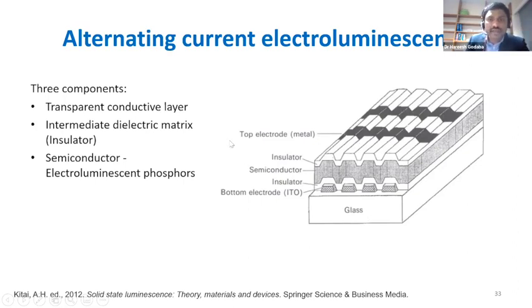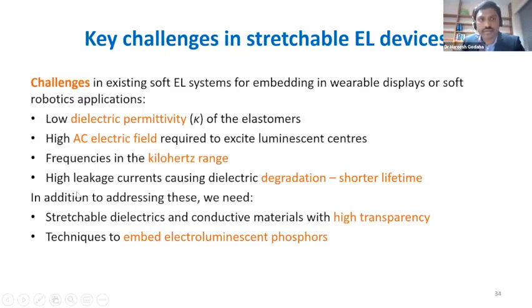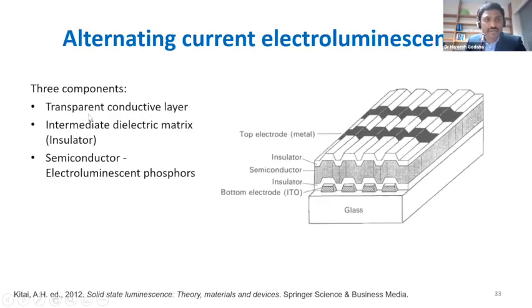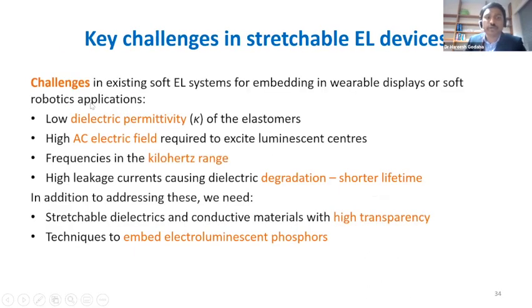Okay, and now if you want to make an ACEL device that is actually stretchable, the challenge is that all these parts need to be stretchable, right? So the key challenge in developing a stretchable electroluminescent device is that we need this dielectric matrix, right? For most soft materials, the dielectric permittivity of the elastomer is low, which may result in low luminescence. And because of that, we need a high AC electric field to excite the luminescent centers, and the frequency needed so that the intensity is above the visible threshold is quite high.